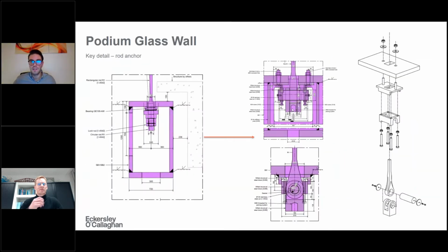So what we allow here is a threaded opening for a bar to be slotted in, coming from this other opening we have at the bottom of the flange. Once the bar is threaded, it's connected to a hydraulic jack which pushes against the bottom flange of the beam. And once everything is locked in position, we can insert a shim to lock the position of the rod and the pin, and also add these bearing bolts, which will be threaded against this steel block, and will clearly bear against the top flange of the beam to lock in position the rod and keep the pre-stress.